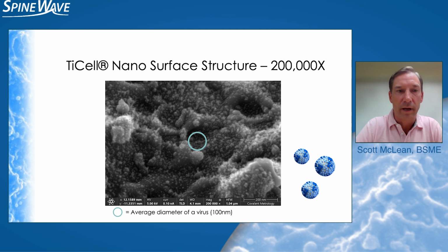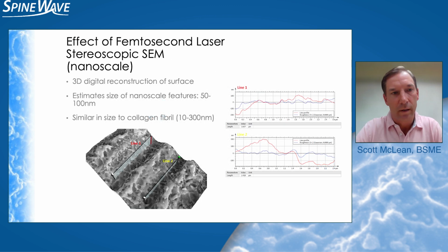As we look at these features now, you can see that they're blurred a little bit, but the melt and recast of the femtosecond laser has left these nano-sized features that are similar in size to collagen fibrils. Again, collagen fibrils roughly being 30 to 100 nanometers in size. And again, using stereoscopic SEM, this time orienting the planes between the ridges, we can deduce the size of those nanoscale features and compare to the size of the collagen fibril.